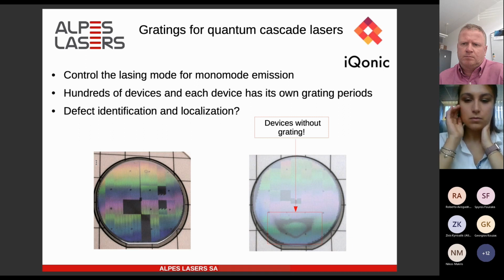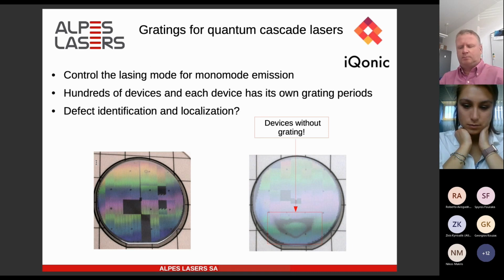And as you can see in the right-hand side image, we sometimes have some defects. If you look inside the red square, you can see some areas which are gray, meaning that there is no grating, etched during the process. So for some reason, in this area we don't have any grating on the top of the devices, and they can be considered defective devices.